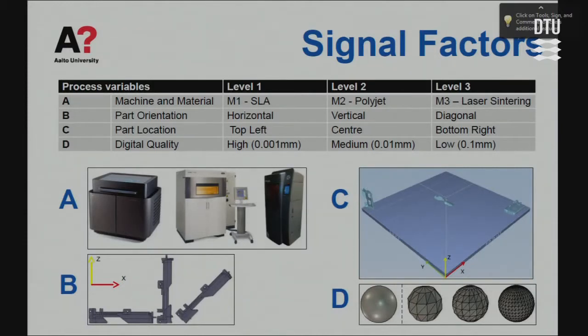And the other parameter was not that easy to include, because I didn't even know at the beginning that it has an impact, but actually it does. Depending on the technology, if you print, there are temperature changes depending on where you are printing, and in fact this has an impact on the accuracy you get in the printed part. Also, if the laser is on top of the tray and has an angle, the projection of the laser beam is different than from the center. And if you go to really measuring microns, it has an impact. So it has issues with the machine architecture. And the last one, I mentioned it, part location: top left, center, and bottom right.